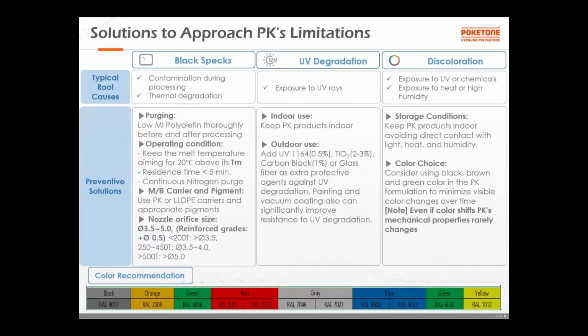Weaknesses: we have 3 weaknesses, black specks, UV degradation, and discoloration. To improve the black specks, we should keep the melt temperature 20 degrees C above the melt temperature of our polyketone. And also, definitely, if the residence time is not that long, it will be better. And we have to purge nitrogen when you do injection molding and extrusion molding, then it will be very helpful to reduce the black speck issue.